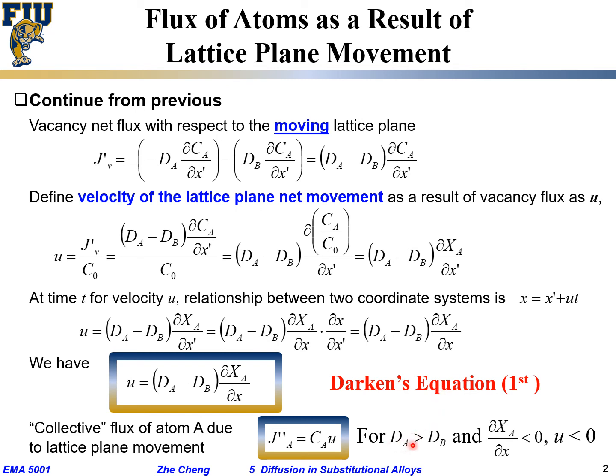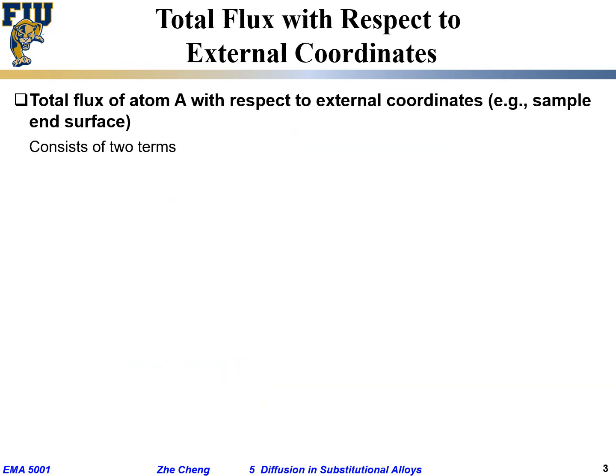And then if dA is greater than dB, and the partial differential of concentration with respect to x is smaller than 0, the velocity is actually negative. Which means, okay, on the A side, this gradient is negative, which means the left side may be higher in A, the right side is higher in B. Higher in A goes towards B, and if dA is greater than dB, actually everything moves backward, negative. Okay? So then let's consider the total flux.